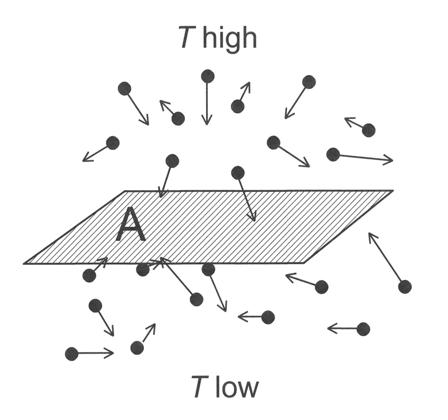temperatures. At higher temperatures, ħω₁ = ħω₂ + ħω₃, and quasi-momentum q₁ = q₂ + q₃ + G, where q₁ is the wave vector of the incident phonon and q₂, q₃ are wave vectors of the resultant phonons, may also involve a reciprocal lattice vector G, complicating the energy transport process. These processes can also reverse the direction of energy transport.